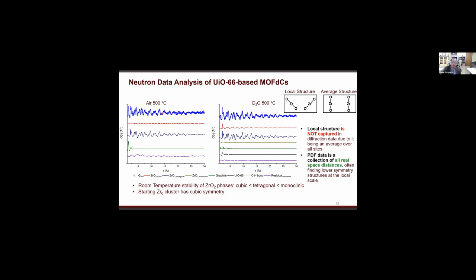As you can tell from here, on the left-hand side it's the 500 degrees Celsius under air for the calcine, and then D2O, 500 degrees Celsius. And see this, the green is against the graphite or graphitic carbon, and those are the different phases of the zirconia: tetragonal, cubic, and monoclinic. After this refinement, for example in air, this one dominates, the tetragonal zirconia. And on this side, with D2O at 500 degrees Celsius, you do see some other phases as well. Overall, you can fit this data pretty well.